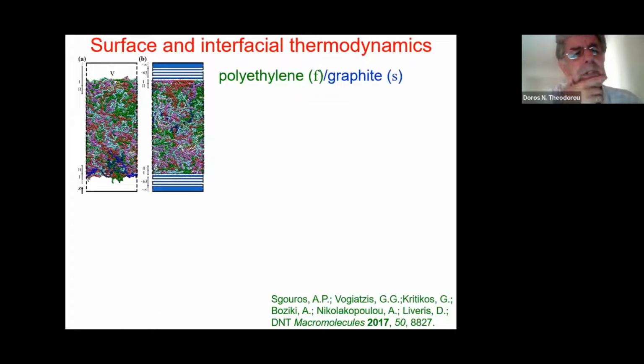Now, a few words about interfaces, since they are so important in the nowadays materials world. It is quite straightforward to simulate free surfaces of polymer melts, or polymer melts sandwiched between solid surfaces, solid polymer interfaces, in other words. Here you see pictures of a polyethylene film characterized by two-dimensional periodic boundary conditions and exposed to vacuum on both sides, and the same film being capped by graphite phases at the top and the bottom. Of course, we need a potential to describe these interactions, and we used Steele's potential in this particular case for the graphite.